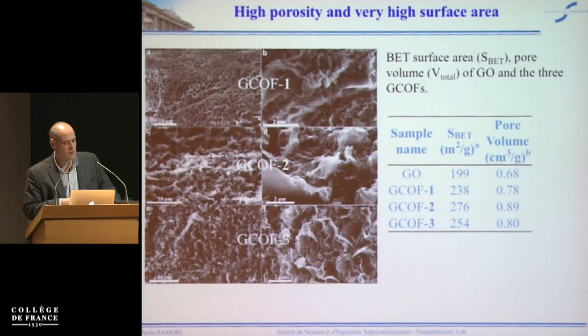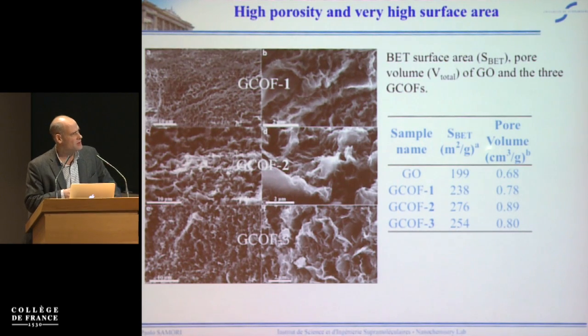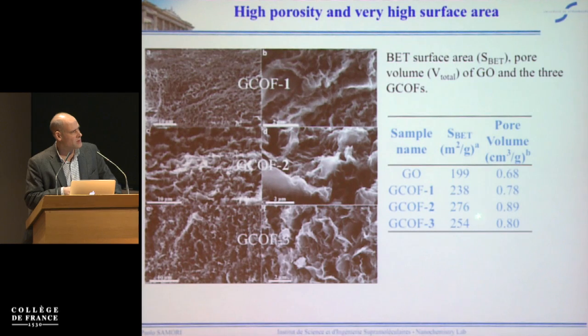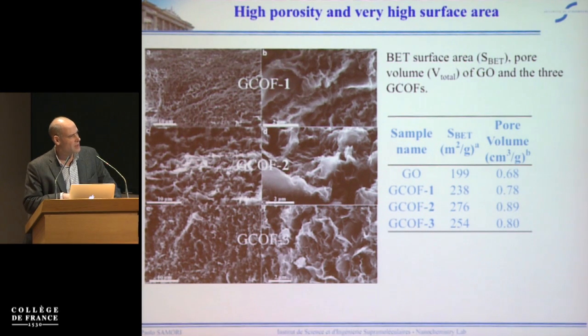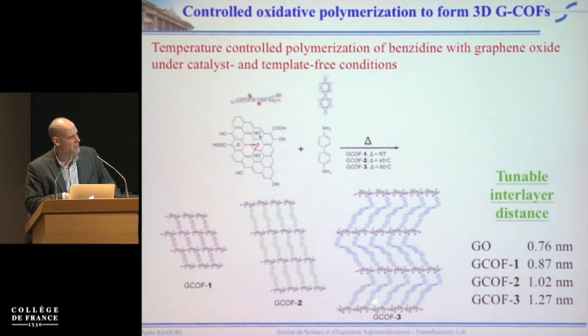Now, this, of course, is also reflected in an increase of the porosity, and so the surface area is increasing, in particular going from GO to room temperature to 45 degrees. It does not increase further when we further increase the temperature, and the reason is very simple. You can see here that, due to the finite persistence length, the benzidine oligomers start to adopt not a vertical configuration, but rather a bent one, and so the surface area does not increase linearly.